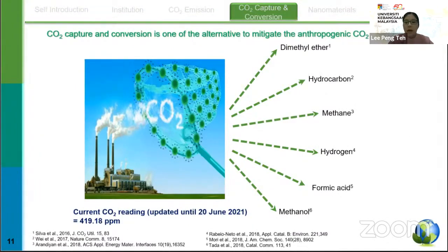In this case, it is important to capture the CO2 as well as convert it to various value-added products like dimethyl ether, hydrocarbons, methane, hydrogen, formic acid, and methanol. Converting CO2 into value-added products is very significant and also a very energy-demanding process. To overcome this energy barrier, we need a catalyst. The catalyst plays a crucial role here to reduce the energy barriers for these reactions.